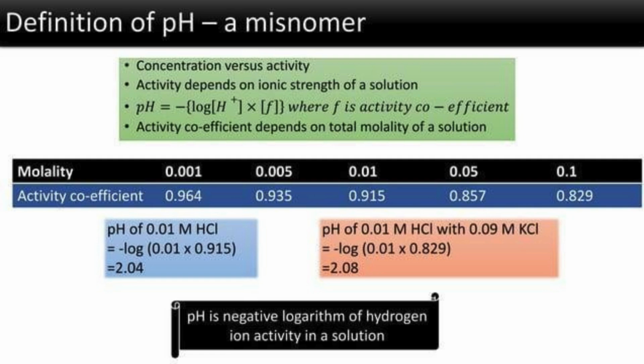For example, at a molality of 0.01, the coefficient is 0.915. So the pH of a 0.01 molar HCl solution is not 2.00, but negative log of 0.01 times 0.915, which is 2.04. If we add more ions like 0.09 molar KCl, the coefficient drops to 0.829 and the pH becomes 2.08. So, to be precise, pH is the negative logarithm of the hydrogen ion activity in a solution.